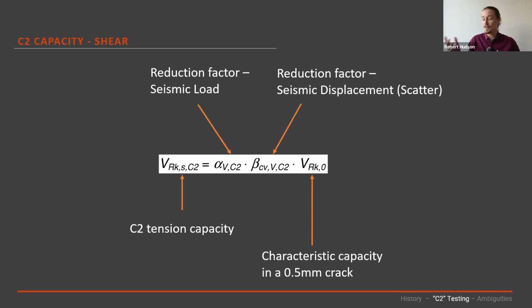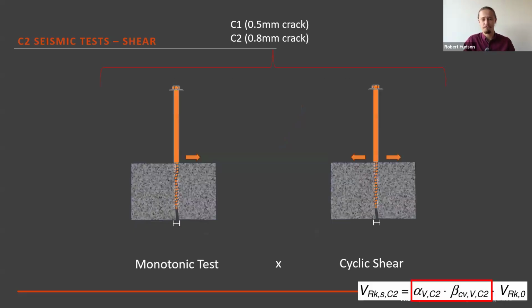All right, that is basically where tension capacities come from, C2 capacities. Obviously, you do a similar sort of thing for shear. I'm not going to go into this in the same sort of detail, but it is exactly the same philosophy. You start with your base shear capacity, and you have your alpha and beta reduction factors based on the impact of the different mechanisms. Now, one thing that is interesting with shear capacities is we don't run that cyclic crack test. This is because someone did a really nifty study, which has probably saved hundreds of thousands, if not millions of dollars worldwide in anchor testing, that compared the impact of the cyclic shear test and the cyclic crack test on the shear performance of post-installed anchors, and found that the cyclic shear test was reliably more adverse. And so we're able to exclude one of these tests from the shear testing.